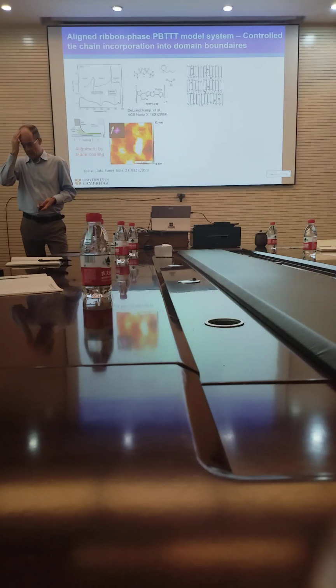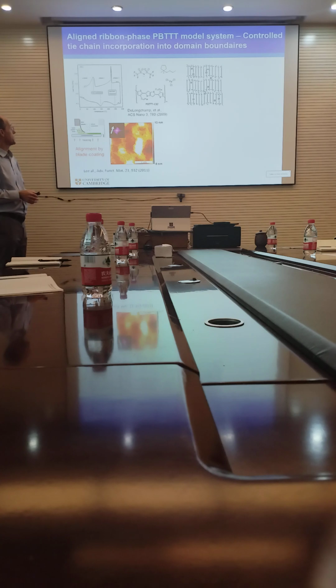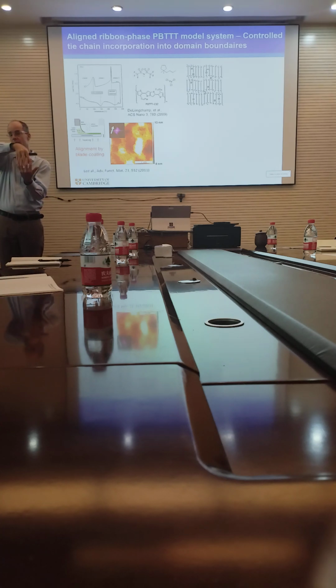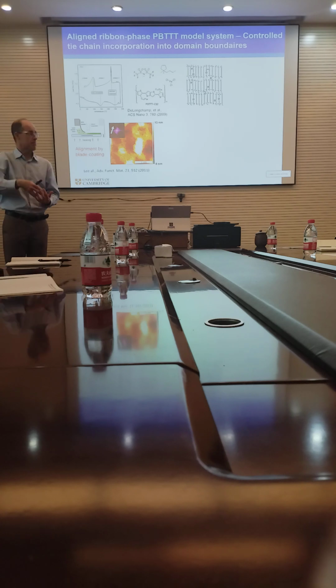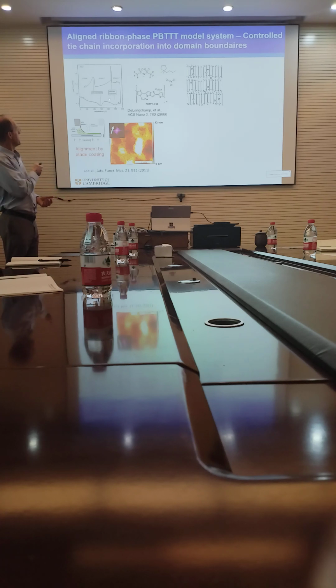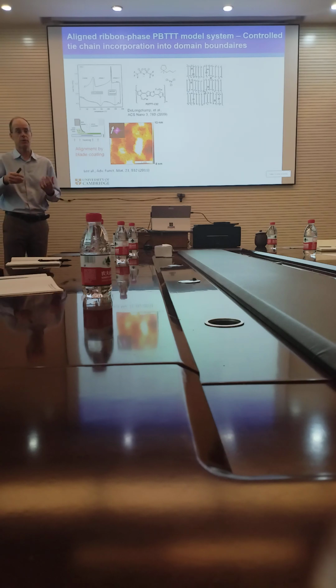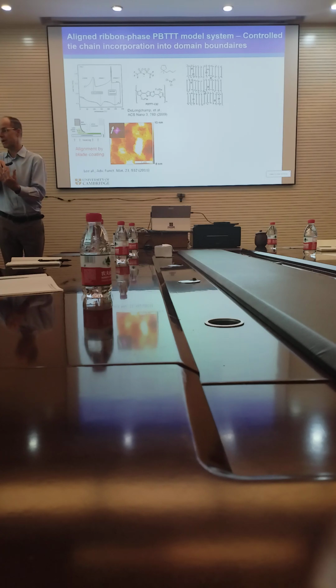We then took it a step further more recently and looked at a phase of PBTTT which we call the ribbon phase. And the ribbon phase is essentially the same microstructure, it's got this interdigitated lamellar microstructure. But on top of that, in the ribbon phase, when you heat PBTTT to temperatures above 180 degrees C or so, it enters a liquid crystalline phase where the polymer chains also adopt some smectic microstructure.